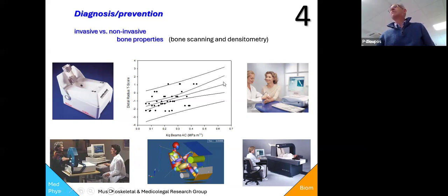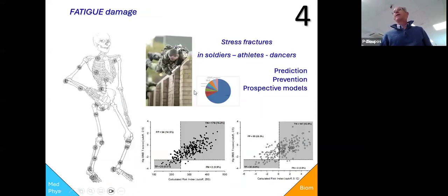So there are relationships. What you see in the ultrasound measurements reflects in the actual mechanical measurements. And these are fracture toughness measurements of the bone of these same people. So there is a relationship, and that demonstrates itself demographically in life, of course, isn't it? So these T-scores do mean something at the material level, mechanical level.